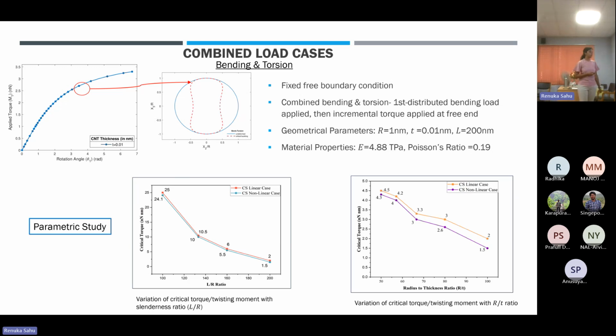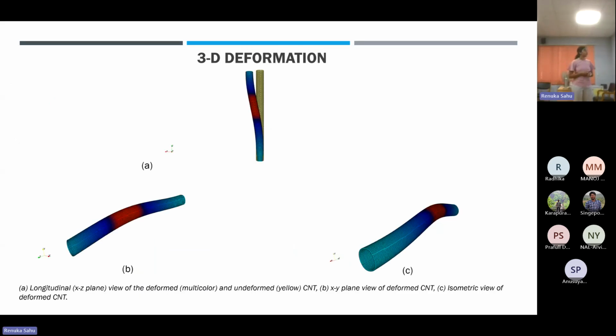We did the same parametric studies here as well, and the difference is evident even for the bending and torsion cases: for higher L/R ratios and higher R/T ratios, it becomes important to consider the cross-section nonlinearity of CNT while modeling them. The 3D deformations for this case have also been obtained.